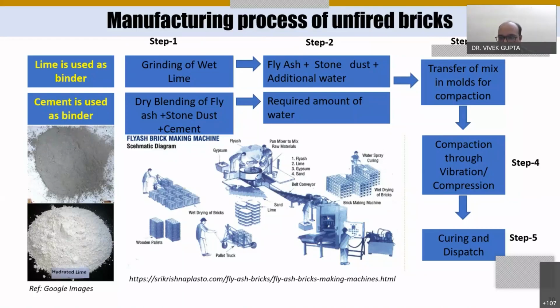Once we compress the bricks, we put them for drying for 2 to 4 days in general. And if the weather conditions are such that the bricks are not drying in one day, then in moist conditions it may go to 2 to 3 days, or in some cases up to 7 days also. Once the bricks are dried, we shift them to the curing area, and then we start water sprinkling curing. After a month, typically we can dispatch them for utilization. But depending on the weather, it may extend to 45 to 60 days, or sometimes 90 days also. But after 3 months, it almost achieves the complete strength.